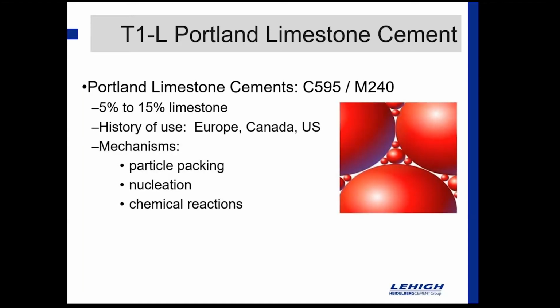There's a few different mechanisms as to why type 1L Portland limestone cement works. Three of the primary are particle packing, nucleation, and chemical reactions. And when you use a type 1L cement, what we have found from our testing is that you can pull a type 1 or a type 1-2 cement out of your mix and typically replace that at a 1-to-1 rate with a type 1L, and you're going to see equivalent or perhaps even improved performance in just about every category that would be of concern to a producer.